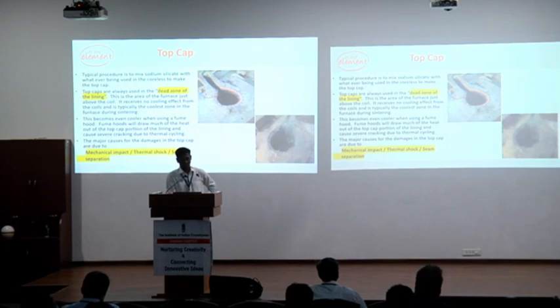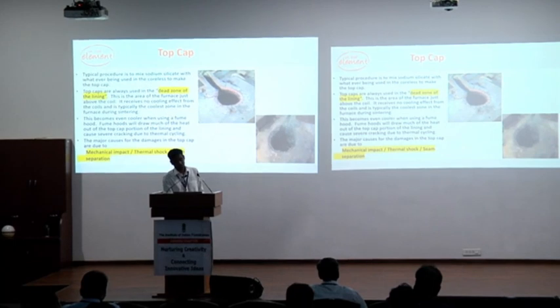The damages in this area are mainly due to thermal shock and mechanical impact during charging, and there's always a seam separation between the main working lining and the top cap, because you have two different components. You have a wet top cap on the top and the dry ramming mass at the bottom, so there's always a seam separation which leads to metal penetrations. This requires daily maintenance, which adds a huge cost with respect to refractories.